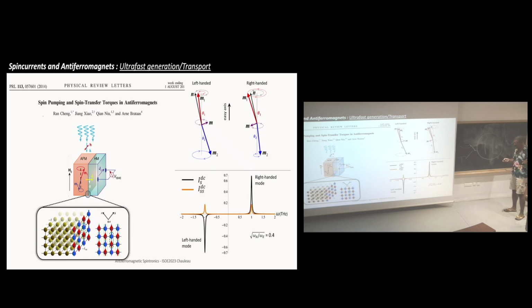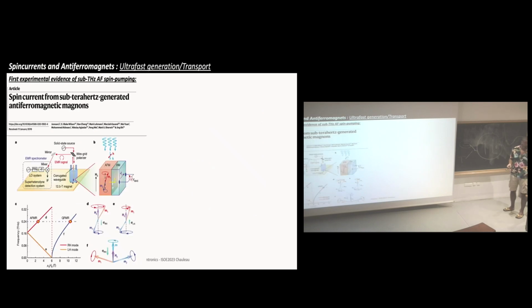Where, if you drive directly the resonance of the antiferromagnet, you will have exactly the same effect as in a ferromagnet. It will drive a spin current, and this spin current can be converted into charge in, let's say, a heavy metal. That was proposed by Cheng, Xiao, and Brataas in this group. It's really the equivalent of this. The nice thing is that it has been proven experimentally as well, quite recently. What people have done is they have taken Cr2O3 this time.